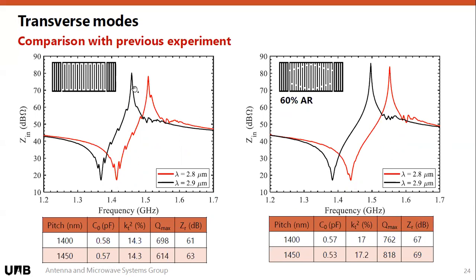We had no apodization. So we had an IDT like this one here. Thanks to the thickness of the electrode, we reduced the spurious modes above the anti-resonance of the resonator, but then we had the in-band transverse modes. Thanks to this 60% apodization, so we have an IDT like this one here, we have an almost completely clean resonator. Just by seeing it, RS is going to be the same because we have the same aluminum, so we have the same value here, but see how high we have gone in terms of Q or of impedance at FP, just by comparing them on the table.